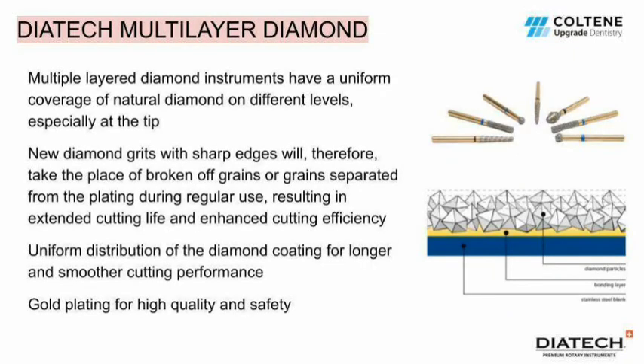DIATECH Multilayer Diamond are multiple layered diamond instruments having a uniform coverage of natural diamond on different levels, especially at the tip. New diamond grits with sharp edges therefore take the place of broken off grains or grains separated from the plating during regular use, resulting in extended cutting life and enhanced cutting efficiency. There is a uniform distribution of the diamond coating for longer and smoother cutting performance, and the shanks of the blades are gold plated, which results in high quality and safety.